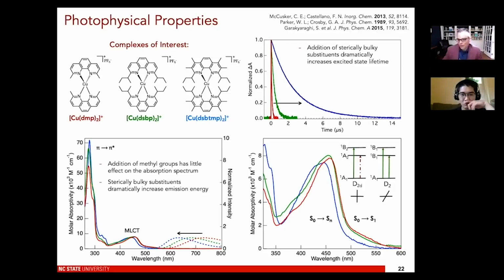And then the idea is when it's more distorted, that typically is telling you that it has more freedom when you make the excited state to then distort even further. And that's why it ends up being a red emitting compound that has a peak about 750 nanometers. It's because in the excited state, you go from copper one, which is d10, formally, to copper one, or sorry, I got this backwards. You start out copper one, d10, and then you formally oxidize it to copper two, which is d9. And when you oxidize it to d9, you get this pseudo-Jahn-Teller distortion, which distorts the molecule even further to accommodate the fact that it doesn't want to have degenerate unoccupied orbitals.